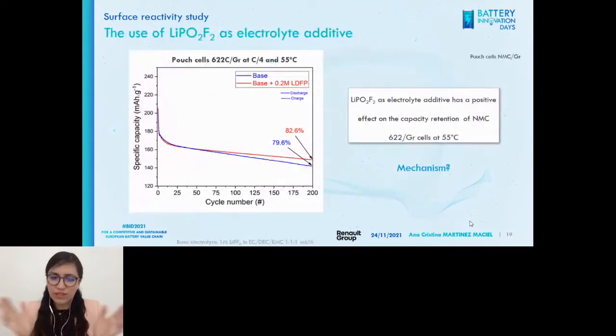So this is one of the results that I obtained. I dedicated one chapter of my thesis to this, so today I will be very brief. We see that, in fact, after a number of cycles - in this case these were pouch cell 622 graphite - after 200 cycles, we can see that when the additive is added, the capacity retention is better. Now, what we asked ourselves, since my thesis was all about mechanisms and chemical reactions, is what is the mechanism through which this additive is working?